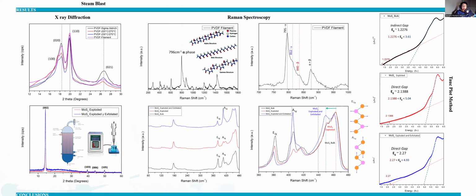So we need to apply TEM and SEM microscopy to confirm the nanosheet morphology, but we already did the UV-Vis absorption, which revealed the band gap expected for high-quality semiconductor molybdenum disulfide. We have the bulk material, which has an indirect gap of 1.2276 and a direct gap of 2.1388, and for the exploded molybdenum disulfide, and a direct gap of 2.27 for the exploded and then exfoliated molybdenum disulfide.